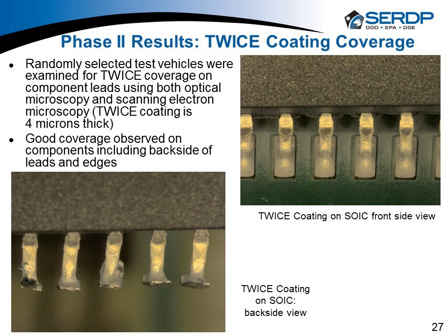Of course, Parylene is the best of all the industry coatings. Vapor deposition can coat everything uniformly. But if you're looking at, say, an acrylic or a urethane or epoxy, the ASG can do a better job of coating. It's on par, the same type of coating that would happen with a Parylene.